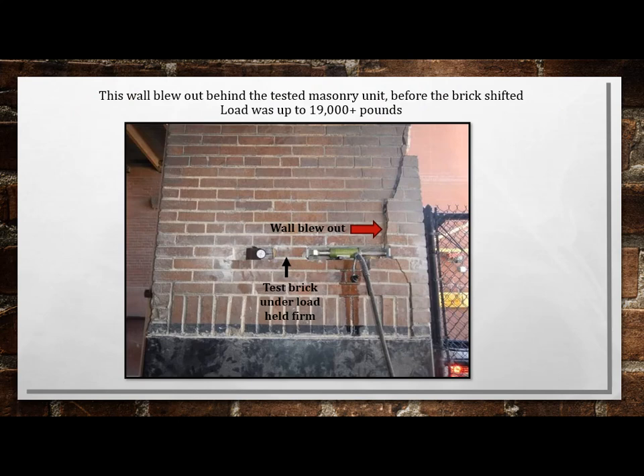So here's one example that this is down at Tum's building. It's very near the baseball stadium by the loading dock. So we were testing the block in the middle where the vertical black arrow is. And so we got our ram on the right, pushing to the left. We got our dial indicator on the left, waiting for movement. So we put over 19,000 pounds on that brick, and it didn't move.